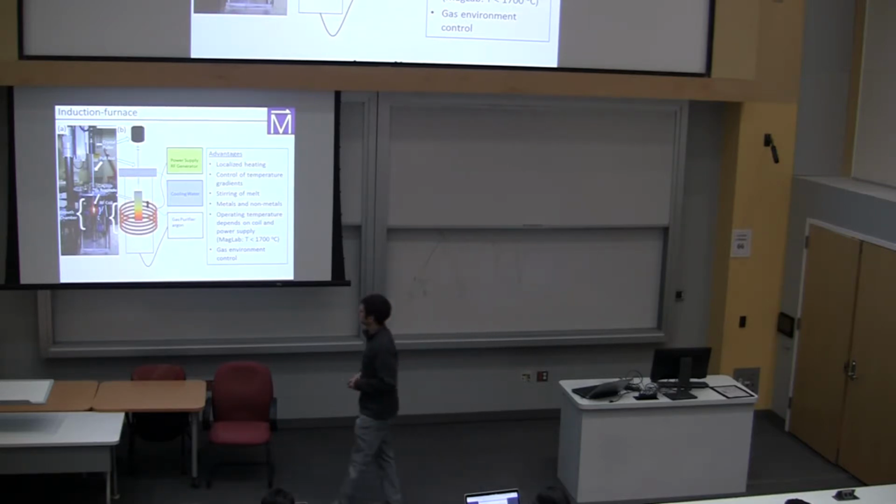Okay, so what we've done here is to build up a system where we have the coil going on the outside of a quartz tube, and then the quartz tube is attached up to a gas flow circuit where we bring in usually purified argon gas because we want to have metallic workpieces in here.